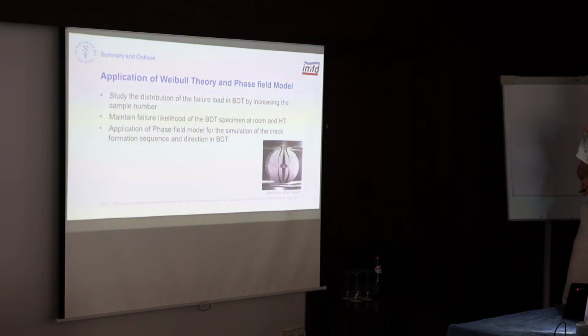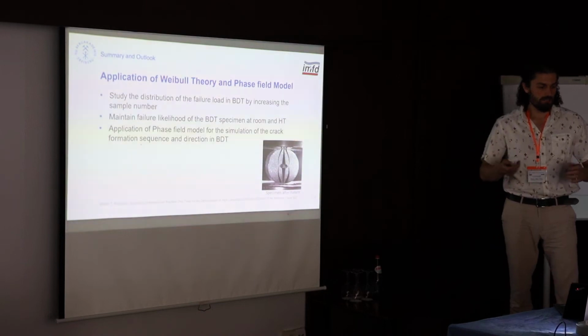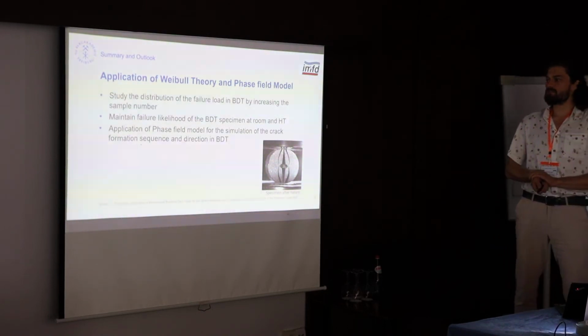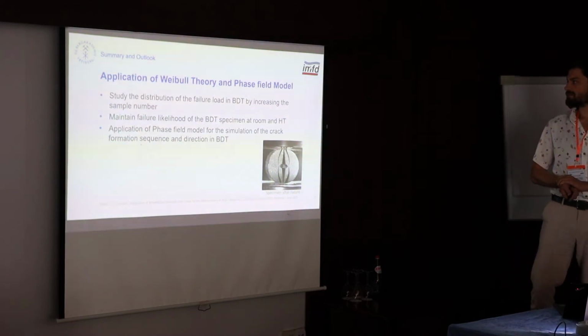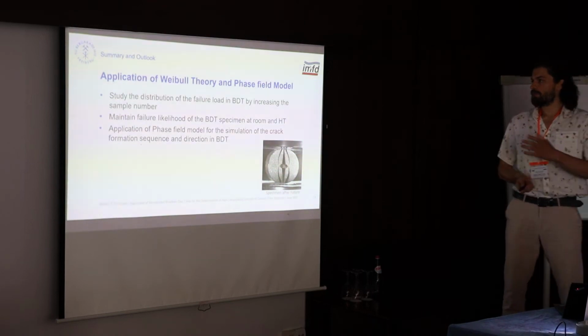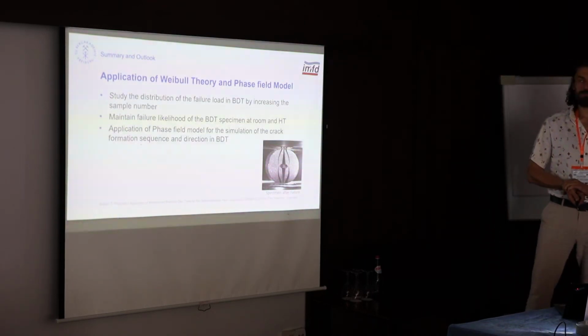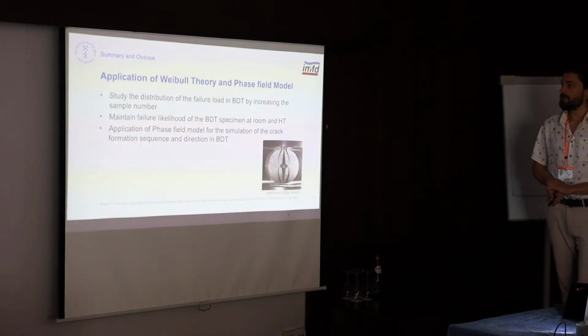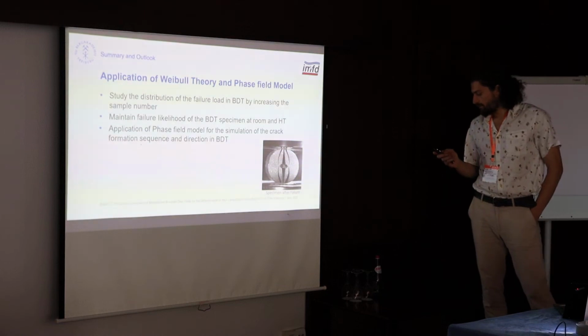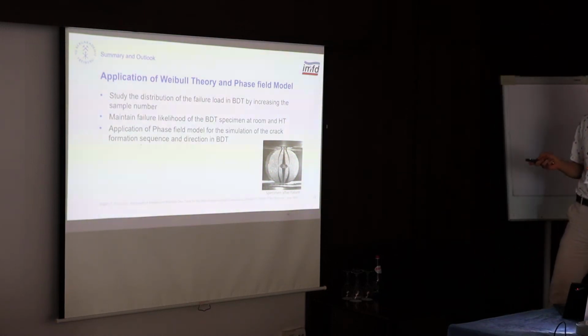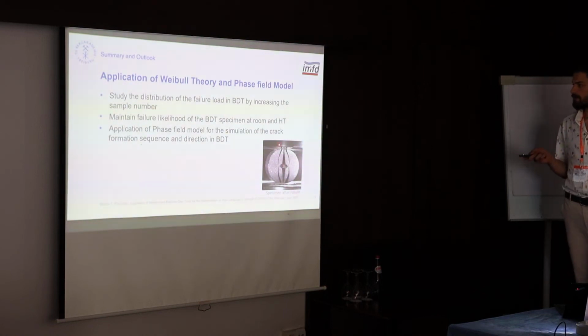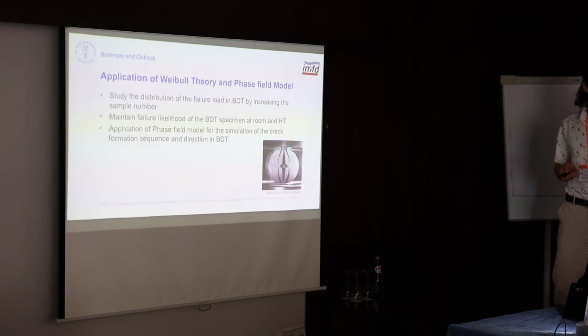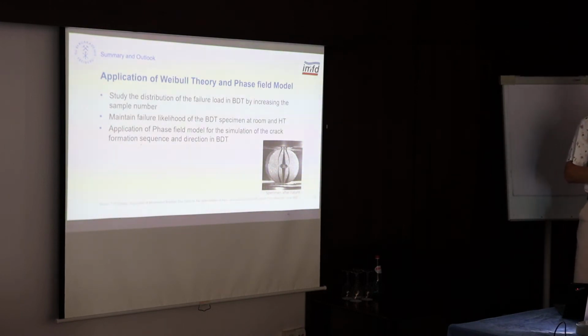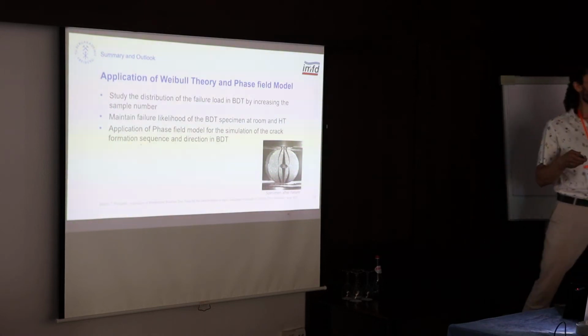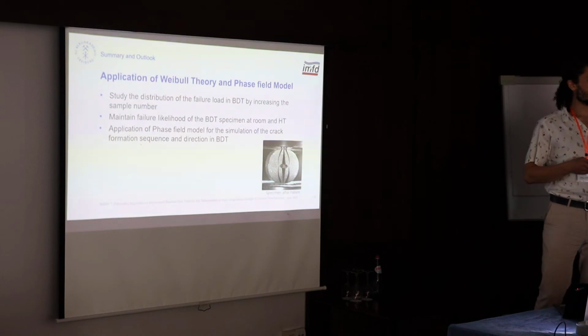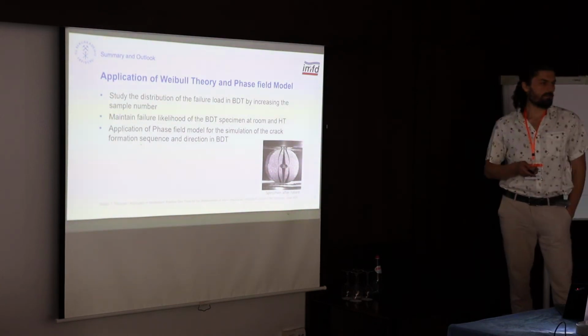So from here I could increase my sample number to get a better distribution of the failure loads for the Brazilian disk test, and therefore apply the Weibull theory to get a failure likelihood of my specimens. As you can see in this picture, the first crack formed along the vertical axis, and then secondary cracks form starting from the contact point. So it would be interesting to apply a phase field model to predict the sequence of these cracks and the direction they are growing to.